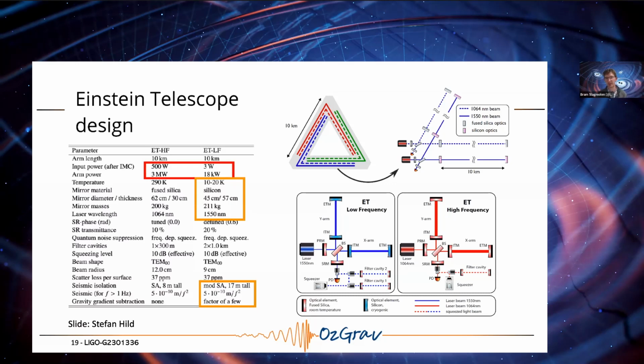And the filters and the squeezing injection are the standard, as Edwige highlighted in the previous talk. A little side note at the bottom, of course, is that for the low frequency, we need to improve the low frequency displacement performance of those test masses. So instead of the standard 8 meter tall super attenuators which Virgo operates, the current path forward is using 17 meter tall modified super attenuators. There's quite a bit of excitement going. So these are the next generation detectors.